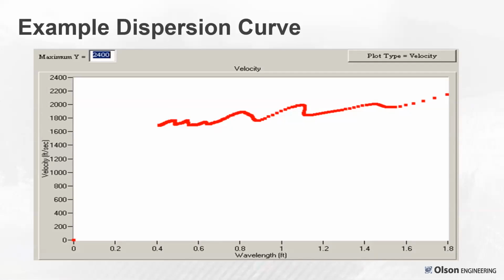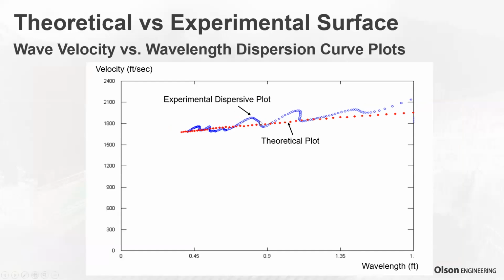So this is an example dispersion curve from the project. It has wavelengths from nominally 0.4 feet, about the first brick, out to 1.8 feet, approaching the wall thickness. And you see a start of velocity around 1700 feet per second, and it goes up to the backside. It got faster with increasing wavelength to about 2200 feet per second. So this is the experimental dispersion curve. And here's the dispersion plot shown with the theoretical plot that fit it. And that's out of the WinSASW software. So reasonably good match theoretically.